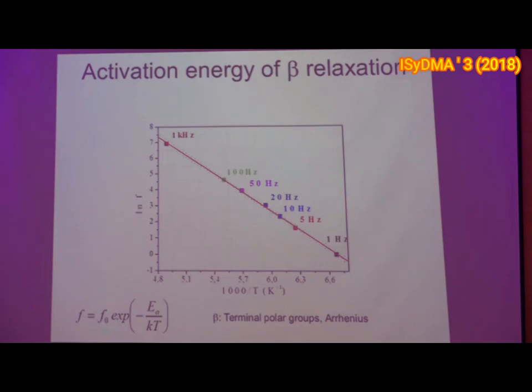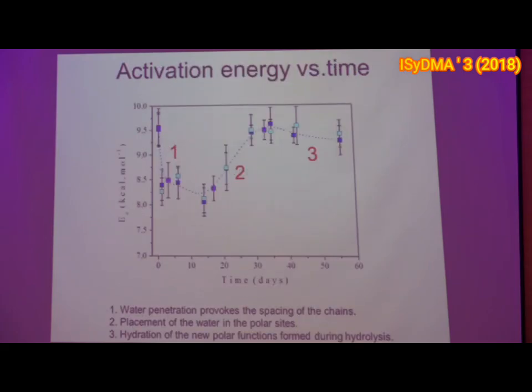And in the case of polymers, we can decide what kind of relaxation we have in this polymer. Is this alpha relaxation, beta relaxation, or gamma relaxation? These frequencies are very low, okay? So this means that it cannot be the gamma relaxation. It will be either alpha or beta relaxation. But for the alpha relaxation, it must be something like that, not linear. Usually we have this VFT model to describe this alpha relaxation. This is a typical beta relaxation process, and when we calculate this activation energy, the values are typical of this beta relaxation, about 10 kilocalories per mole.